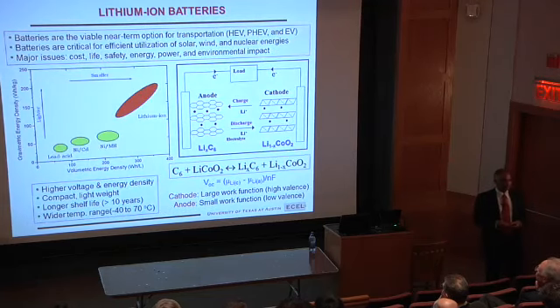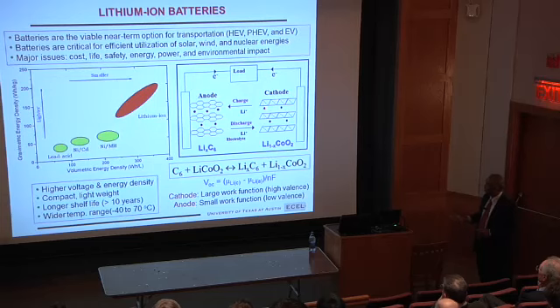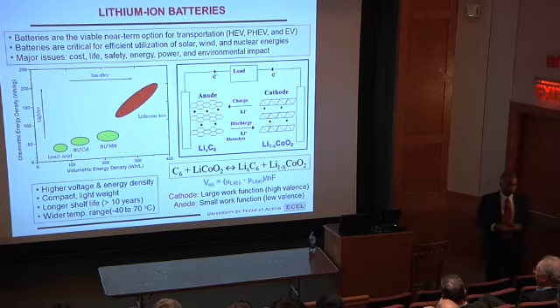So that's not the only thing. You have to keep the voltage as high as possible without damaging the electrolyte. I should be able to store a lot of charge in these two anode and cathode materials to have the energy density. So right now, the technology is based on insertion compound electrodes. Graphite, you can store 1 lithium out of 6 carbon. That's the maximum it can store.